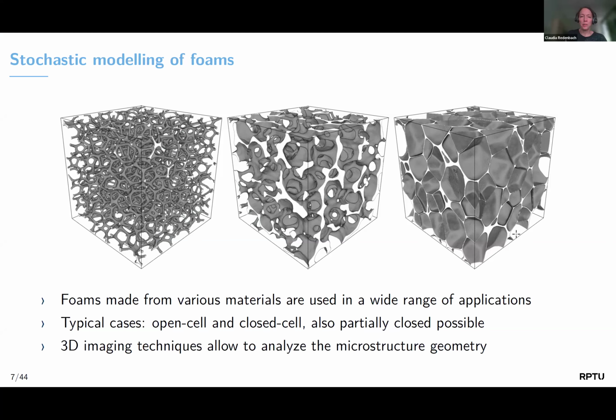And you see here a range from open cell foams, just consisting of the struts, to closed cell foams, but you also have hybrid versions where you have some open cells, but also some closed walls present. Foams are typically very nicely imaged in 3D by micro CT. They have a very high porosity. There's usually just one material present that you have to distinguish from air. And therefore, CT is a nice method to visualize and analyze the microstructure geometry here.